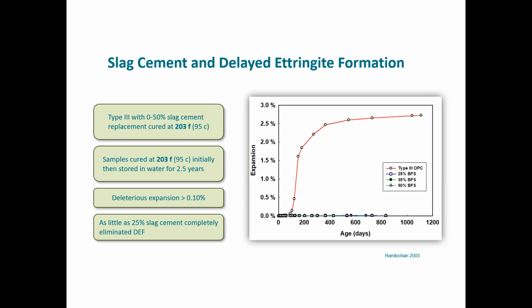And they did 3 different levels of slag cement, and obviously because there was so much expansion in this OPC type 3 mix, and almost none in the 25, 35, and 50% replacement for slag cement, it's very dramatized. But the reality of it is that anything over 0.1% is considered to be deleterious, and you have this OPC mixture over 2.5%, somewhere between 2.5% and 3%. And then you look at the varying replacements of slag, and you can't even hardly see them.